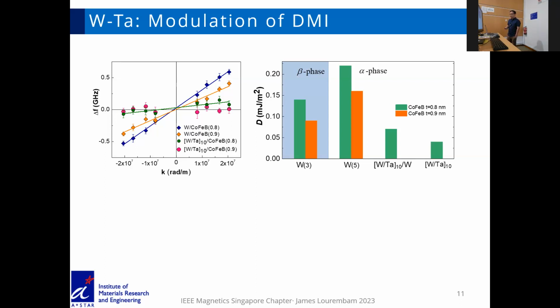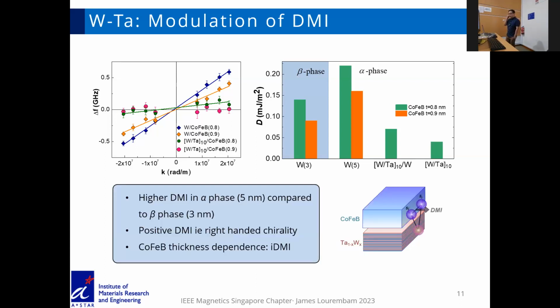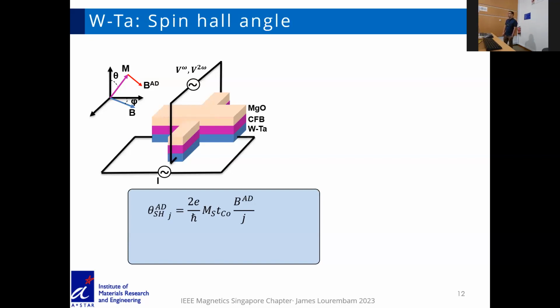Once we alloy, we could tune the DMI by up to about 70% with different combinations of tungsten and tantalum. The other thing here is that, as mentioned in the literature, we also got positive DMI, or right-handed chirality, for all the samples that we measured. The second parameter that we wanted to optimize is the spin Hall angle. For this, we fabricate Hall bar devices and do first and second harmonic measurements. From the first and second harmonic signals, we can get the anti-damping-like torque field, the B_AD here. And we can use this B_AD term to determine the spin Hall angle in the system.